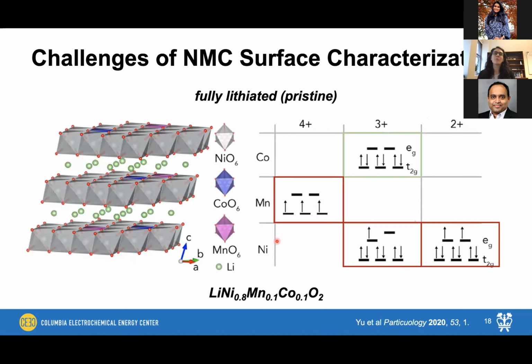So if we think about NMC811 and we look at the electron configuration of all of the different transition metal centers that we have in this material, let's take just the pristine material that we have here. We have our nickel, it's in a mixed 2+, 3+ oxidation state. Both of those are paramagnetic. Nickel makes up 80% of our transition metal centers here. So this is already bad news bears.